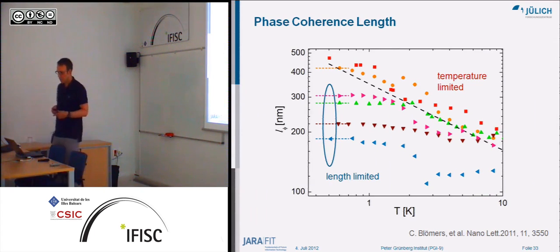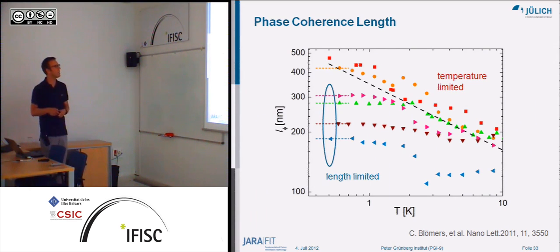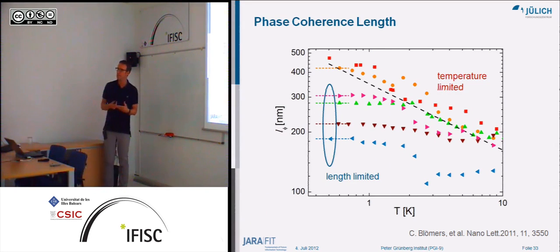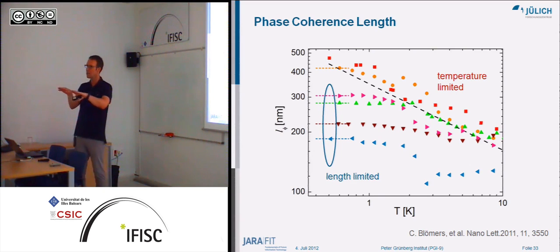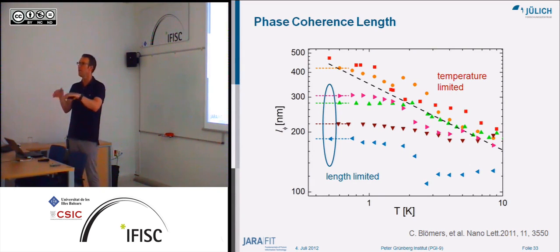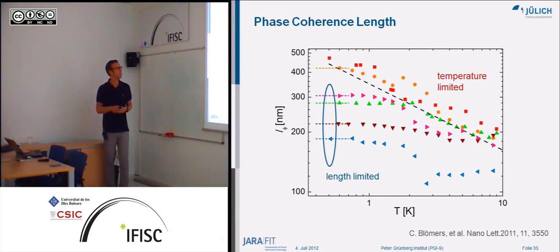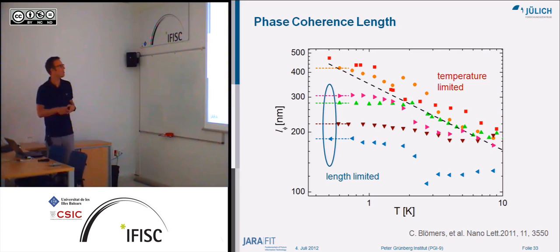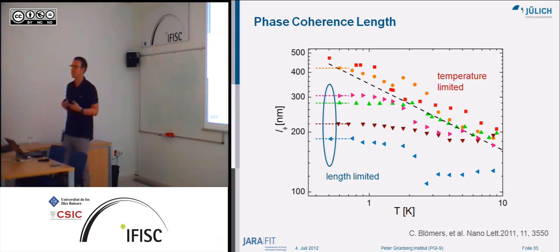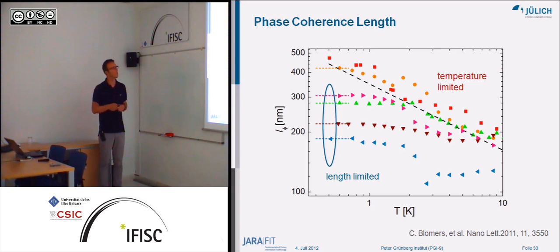And then you can plot this as a function of temperature for different wires here, and you see that the phase coherence length at first follows this line, and then it's cut off simply by the wire length. So that tells you that if the contacts are short enough, and if the temperature is low enough, then you have a completely phase coherent piece of wire there. And if the nanowire is longer, you have to decrease the temperature further. But you see here, to give you some numbers, if you have less than 1 Kelvin here, you have phase coherence lengths in the order of several hundred nanometers, so 400 nanometers in that case.